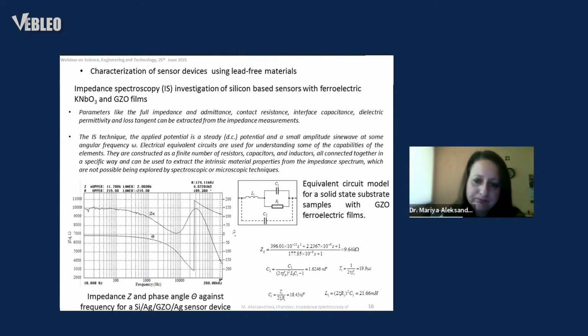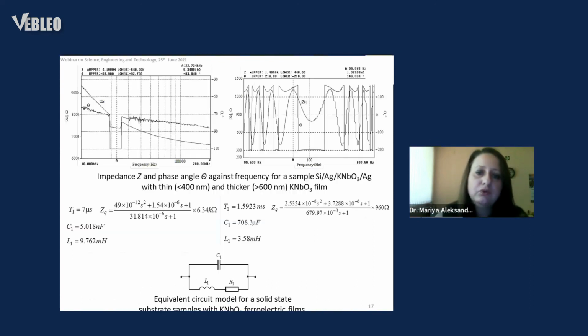So we did this for the potassium niobate, we determined its equivalent electrical circuit. We calculated from the model that better fits the experimental results the concrete values for the capacitance of the interface, internal resistance, full impedance, and parasitic components, etc. And we did the same for the gallium-doped zinc oxide. The previous one was for potassium niobate, I'm sorry.